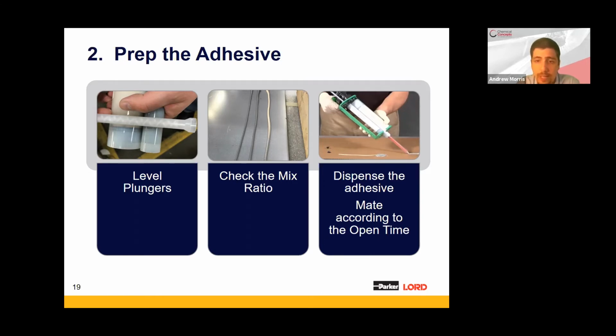Next, you want to apply the static mixer and dispense a bead of adhesive approximately the length of the static mixer. That also ensures that the product that you're actually using on your part is mixed appropriately. And then you always want to check and see the mix ratio.